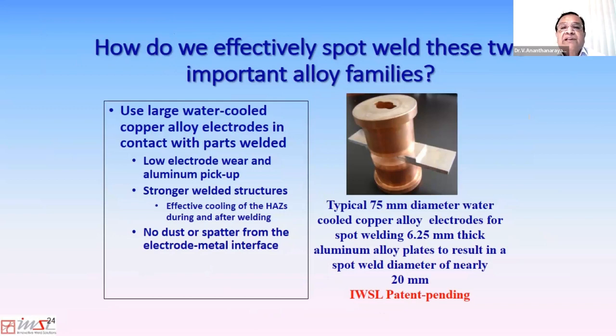And so these large electrodes have low electrode wear, and they last a few thousand hits between redressing operations. As you know, if you're spot welding aluminum in an automotive factory, it's hard to have more than 60 or 70 hits between redressing operations for the electrode tips. And a few thousand hits between redressing operations is almost unheard of. So this kind of a focused melt resistance welding permits the spot welding of these kind of thick and thin metals with very high electrode life. And also there is no dust or spatter from the electrode metal interface.